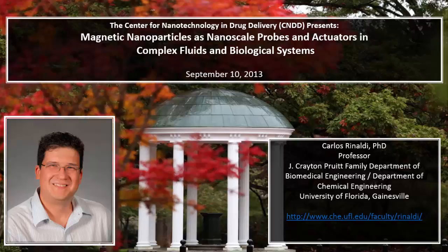For the other things that I'm going to show you, we want to coat them with a polymer that makes them hydrophilic, and we can suspend them in aqueous-based media. In this case, what we do is we modify the surface first with a silane that has functional groups, and then we use these functional groups to react to another molecule, and the molecule can be either a dextran molecule or a polymer, in this case, polyethylene glycol.